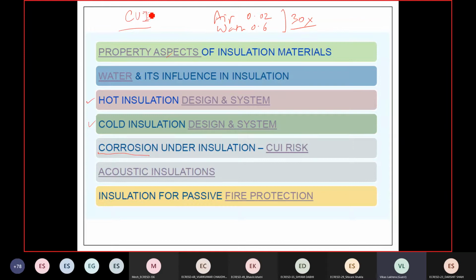wall. Typically, if there is austenitic steel, and the amount of chlorine in the insulation or the sulfur content is not appropriate, then it can cause the metallic walls to corrode. And this is an issue because you will not know unless you open the insulation, and once you have put it in, you will not usually open it periodically. Even for cleaning or other things, it is just put in place, and unless the insulation is bad and has collapsed, we do not usually replace it. But because it is hidden, it can silently cause corrosion.